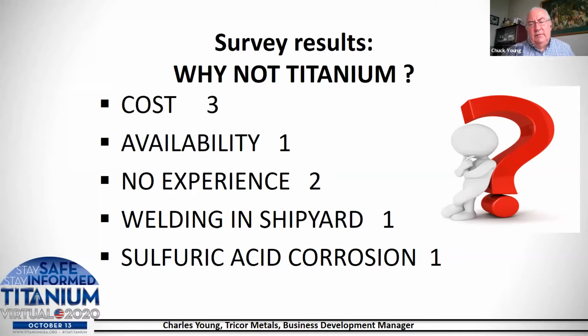This is survey results. One of the things that I asked Bud Ross to put into the survey, because I knew that no titanium had been used in this market, is why didn't the shipbuilders, the ship owners, the shipyards, and especially the scrubber manufacturers or scrubber design firms look at titanium? And we see the typical answers to a question of why don't you use titanium? It's cost. They say it's too high cost. They say it's not available. They don't have any experience with it. One gentleman said that they have no experience and they don't know how to weld it in the shipyard, and they don't know if they can get welders that can weld titanium. And lastly was sulfuric acid corrosion.